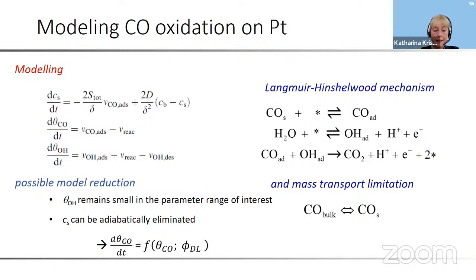Adiabatic elimination means we need to take into account that it changes, but we can assume it changes quickly enough so that we can finally, in the most efficient way, write the equations only for the coverage of the electrode with carbon monoxide. So in this way, it is to be understood that we need only 1 variable.